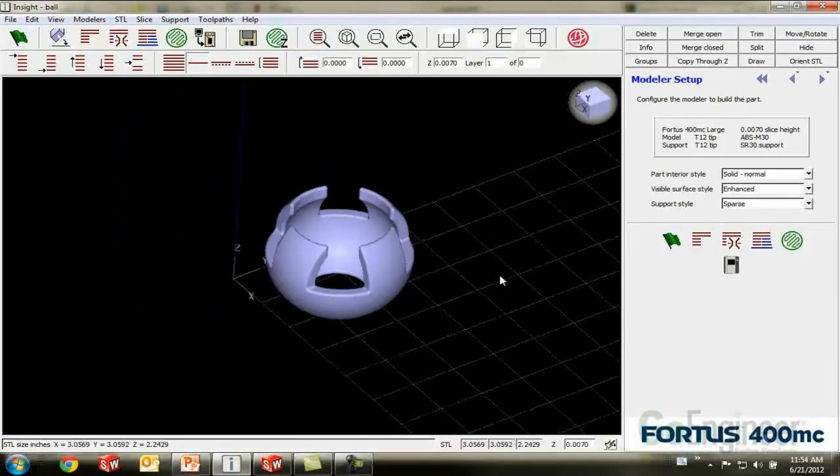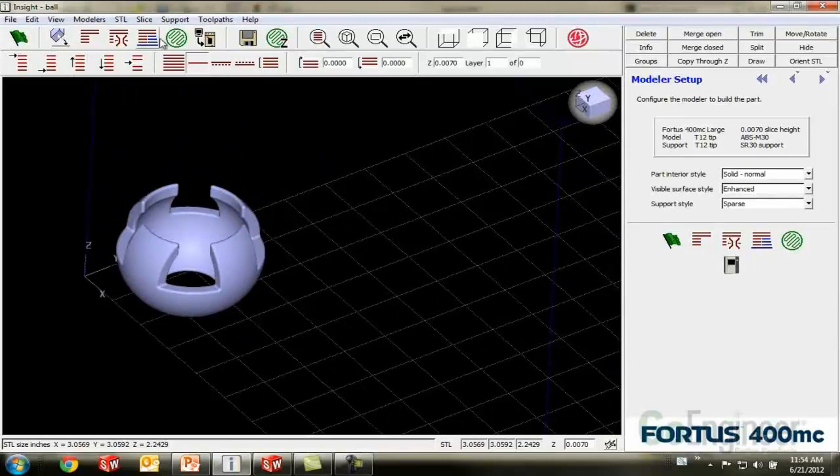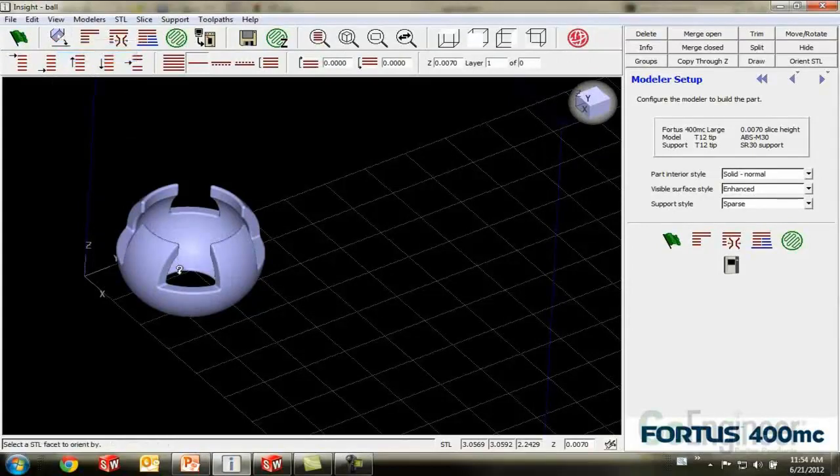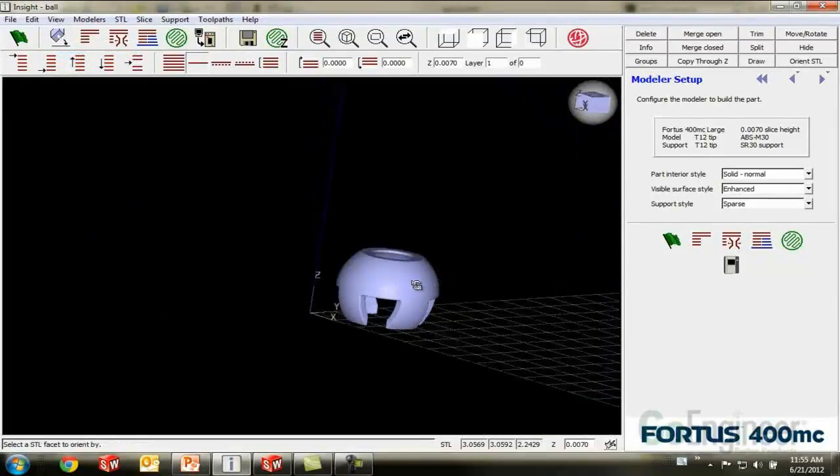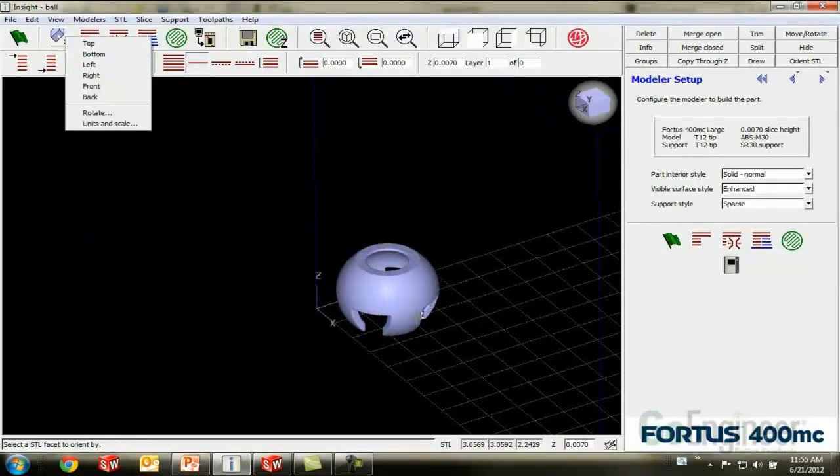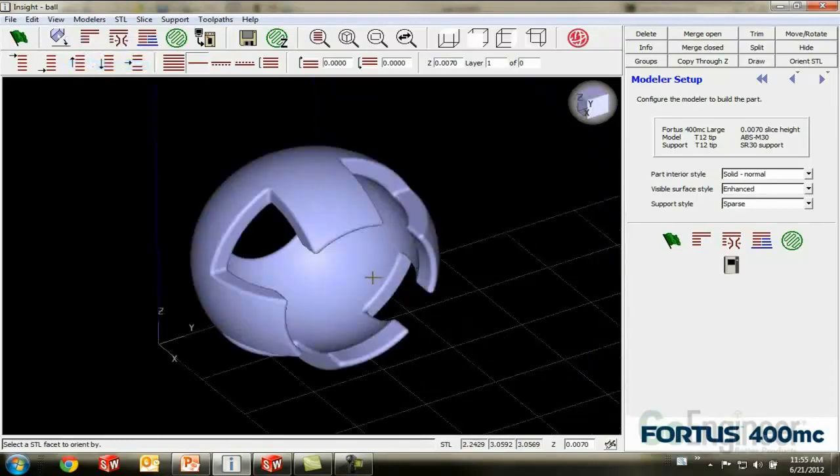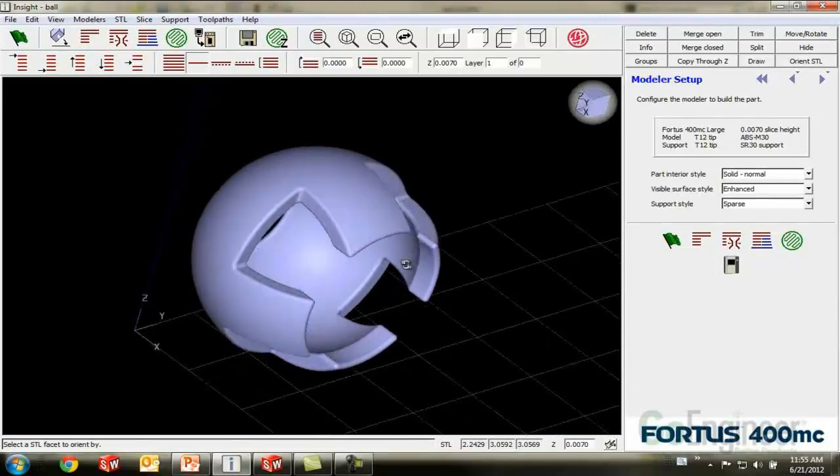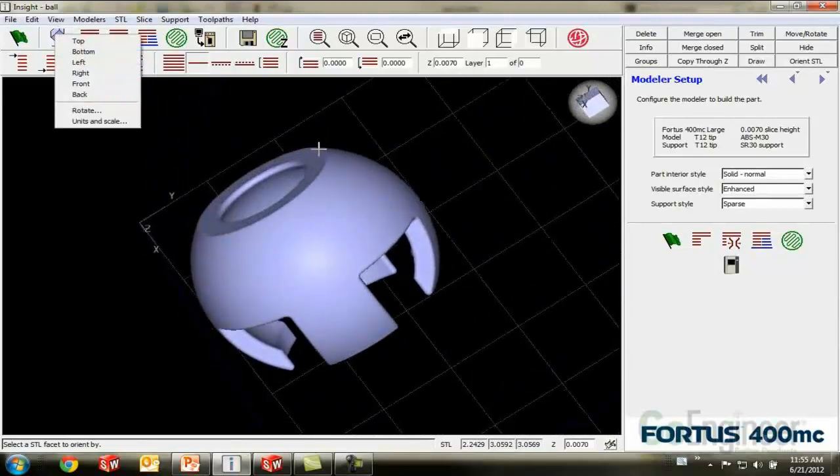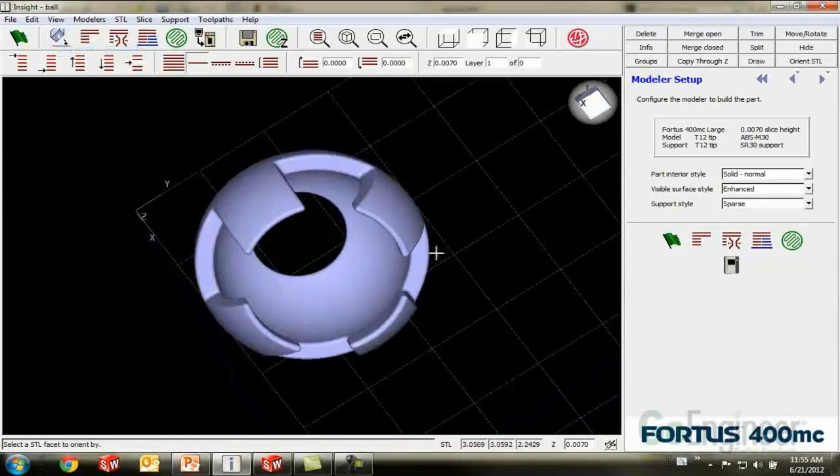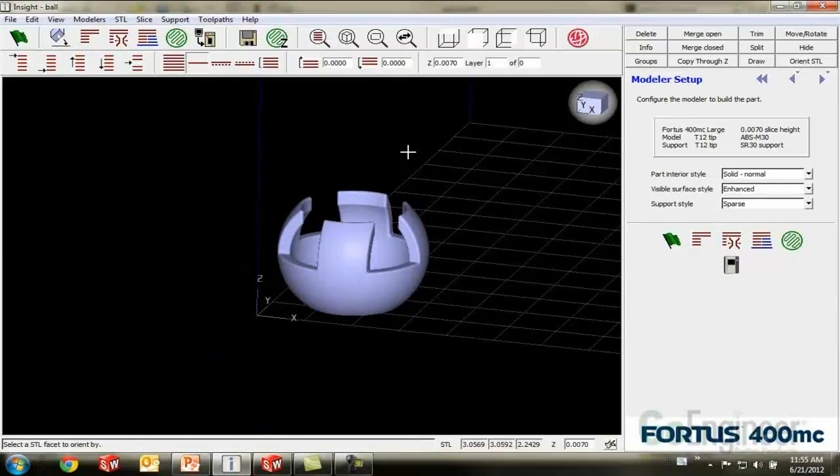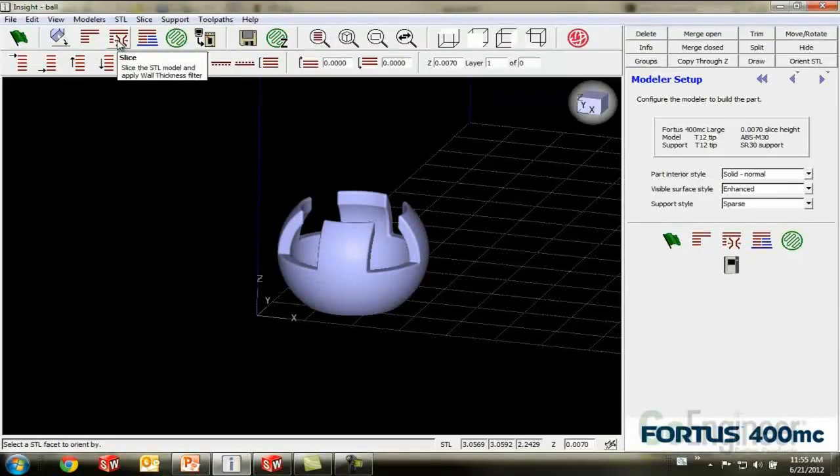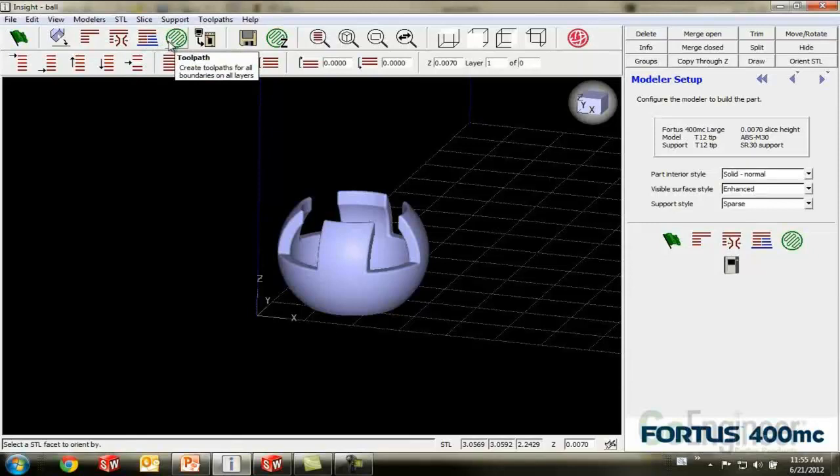Another consideration when you build this is strength. Because it's put down in layers, there's almost a grain to the way that the parts come out. It's very durable going across the grain. But when you go with the grain, it has a tendency to not be as durable as if you went across the grain. For this one, this is actually going to be perfect. But let's say I wanted to make this upside down, flip this around. Really easy to do. In here, I just work left to right. I can say, I don't want that to be the top. I want that surface to be the bottom. You can see it automatically flips it over. Or I can say, I want that surface to be the left side surface. I want to build it in this orientation. But really, this part builds the best using the flat there as the bottom.